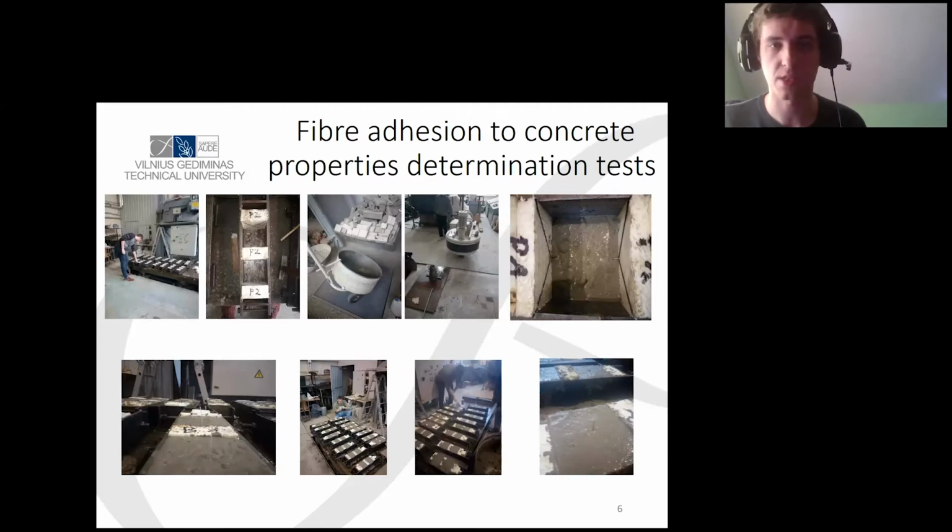After that, we mixed the concrete, performed a concrete slump test, and poured the concrete into the forms very carefully, not to damage or move the fibers already placed. After the concrete was poured in, we put in another fiber on the top of it. Then to condense the specimens, we vibrated the table. And after that, we left it to harden for 30 days.